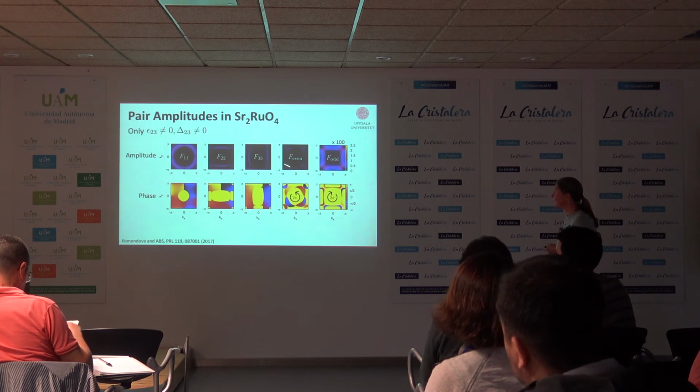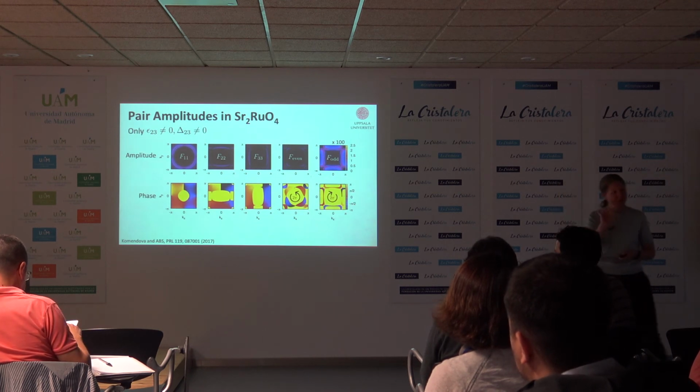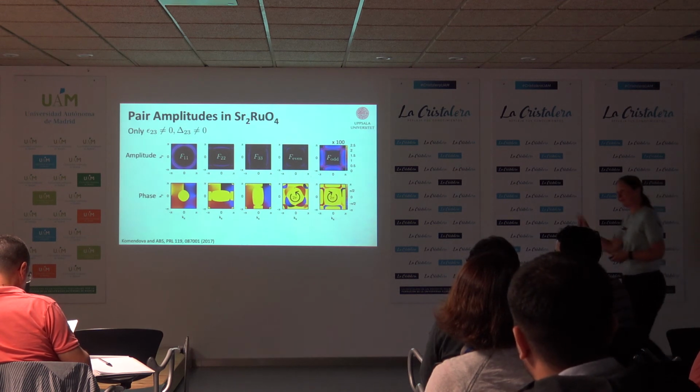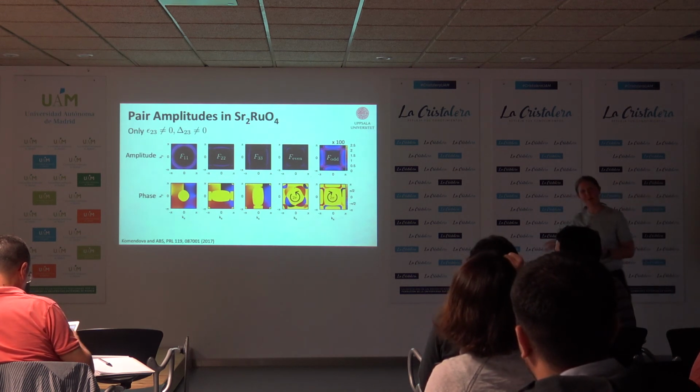Here's the even, and this is the odd, and you see it's small. I have to scale this up 100 times. So the odd frequency state is small in Sr2RuO4, but if there is an intrinsic Kerr effect, it must be there, and the intrinsic Kerr effect is small.